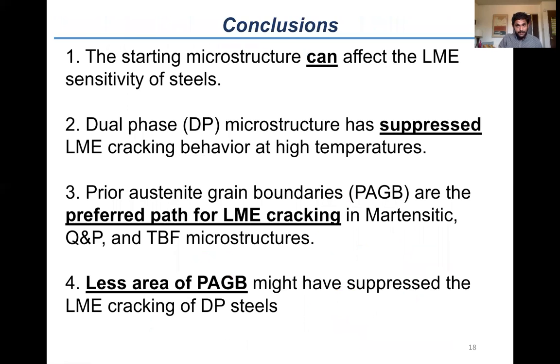And so our conclusion from this study is that the starting microstructure can definitely influence LME sensitivity of steels. The dual phase microstructure has suppressed LME behavior at high temperatures. We clearly saw the dual phase microstructure did not crack sufficiently enough compared to the other steels. The prior austenite grain boundaries were responsible for the similar extent of cracking of the martensitic, TBF and Q&P specimens, and perhaps the smaller area of the prior austenite boundaries suppresses the LME cracking of the DP steels.